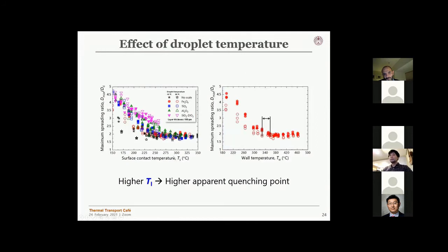Okay, so we've also tested the effect of droplet temperature, and it didn't really matter in terms of the transition of droplet behavior. But what it tells us is that if you have a higher temperature, then you eventually have a higher apparent quenching point, because the surface contact temperature is dragged toward the higher temperature if you have a hotter droplet, if that makes sense. Okay.